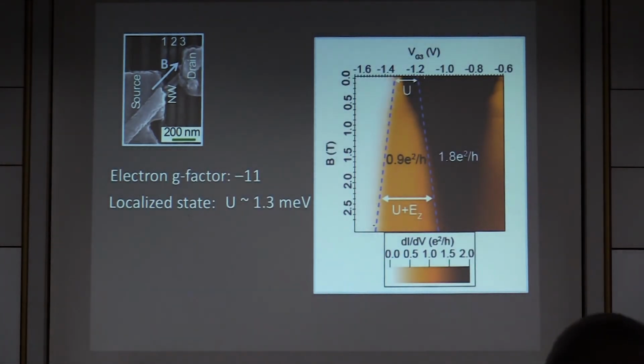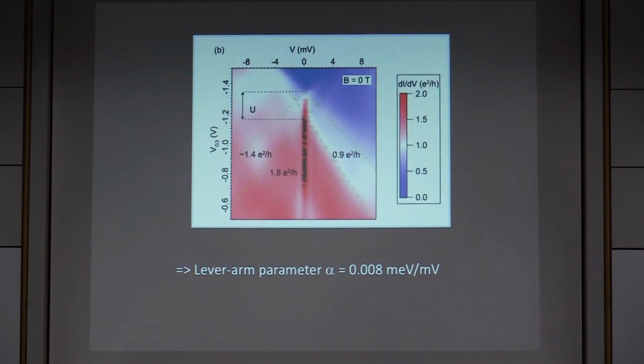Here is the same plot in a color scale, where you can see that the plateau shrinks, but the extrapolation goes to a finite separation of this line. We can interpret this as the presence of some residual charging energy, and so this separation is not simply the Zeeman energy, but it's the Zeeman energy plus local charging energy.